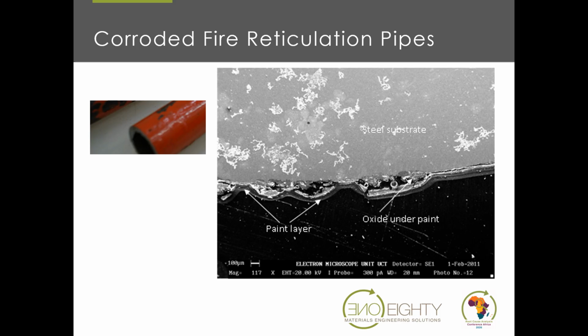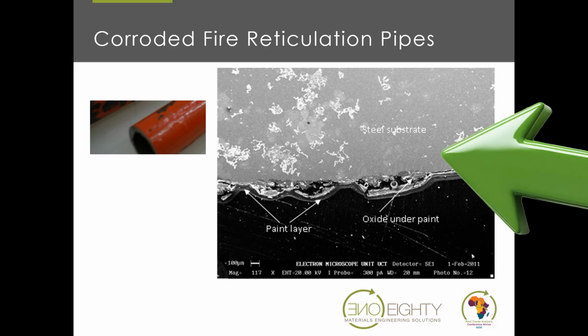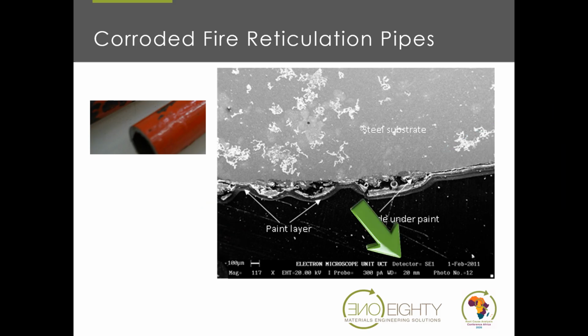And what you're seeing here is a steel substrate. So it is a section through the pipe. If you can imagine this cut in half and then ground and polished, so you have the circumference of the pipe section, and then you can look at very high magnification. In this case, you can see that little micron marker there is 100 micron. And what you're seeing here, because we are using something called the backscatter electron detector, is that we are able to see contrast associated with composition.